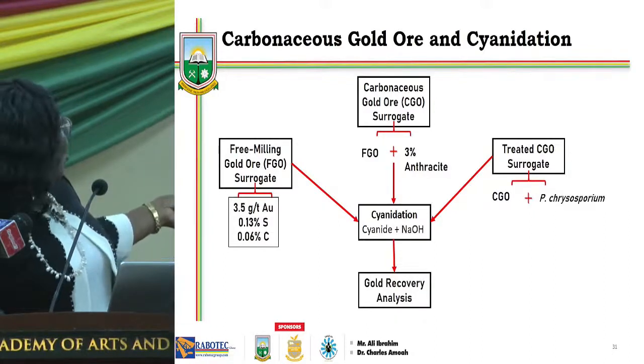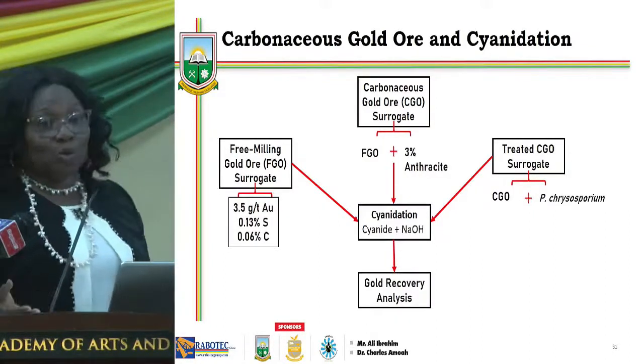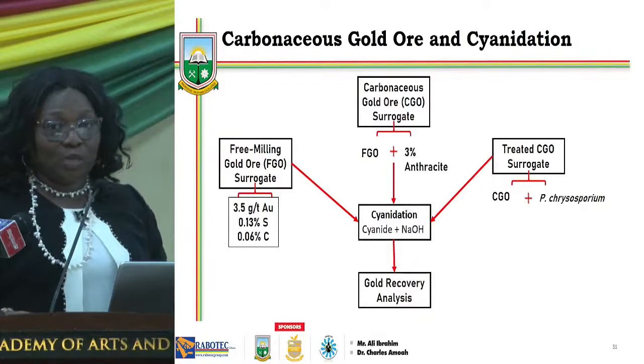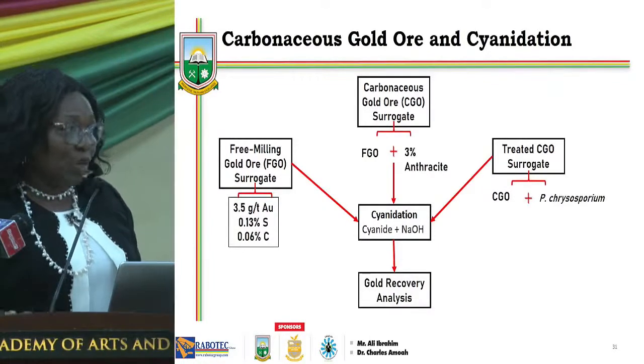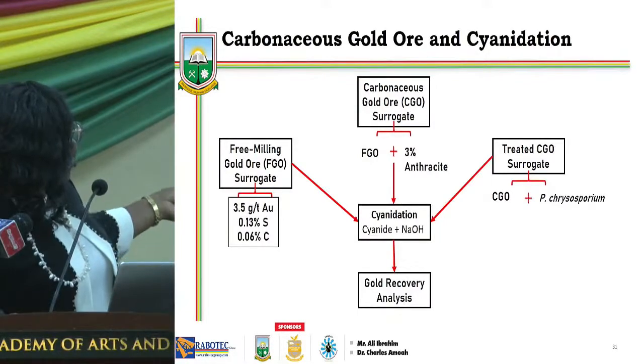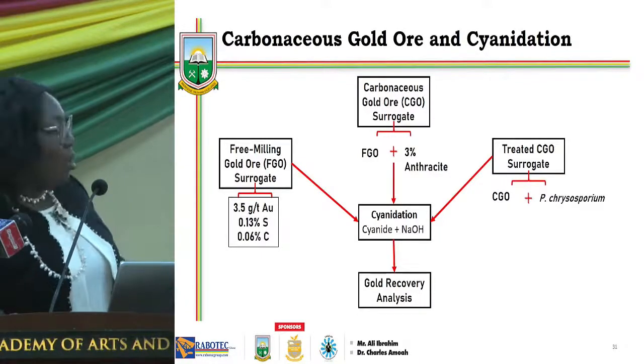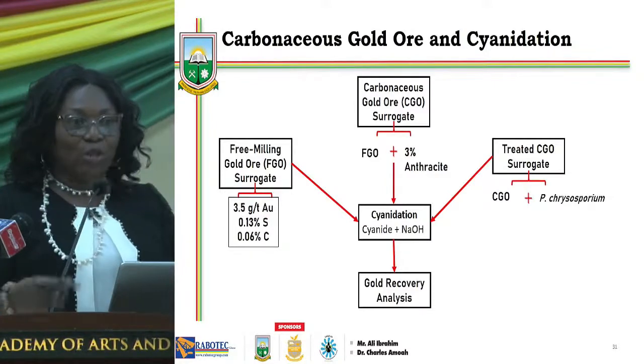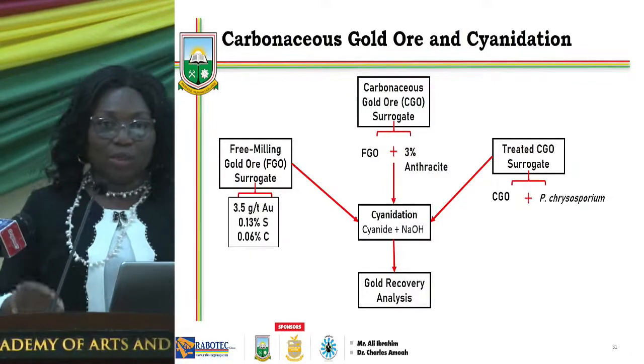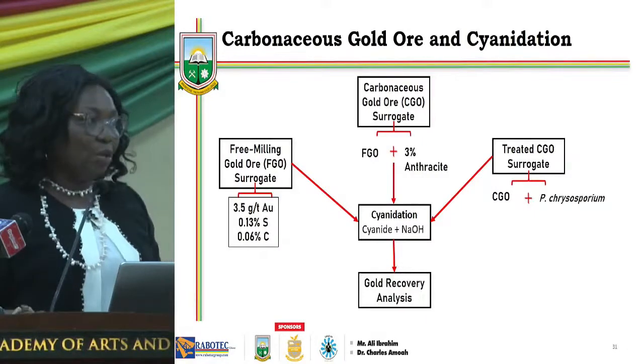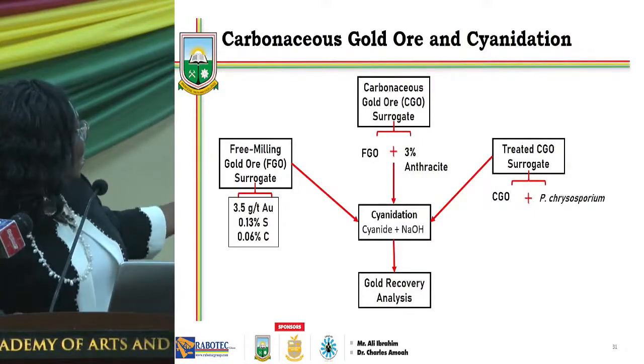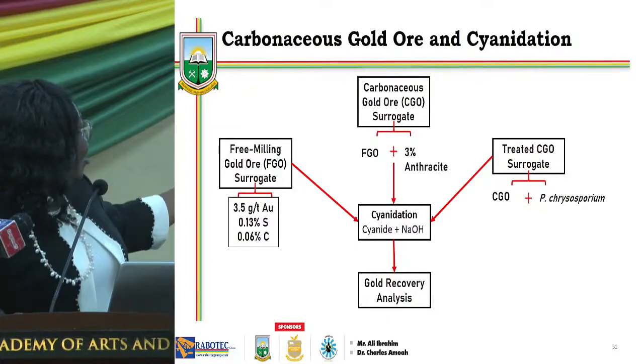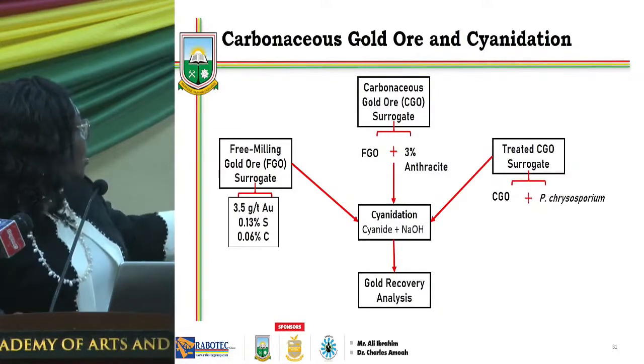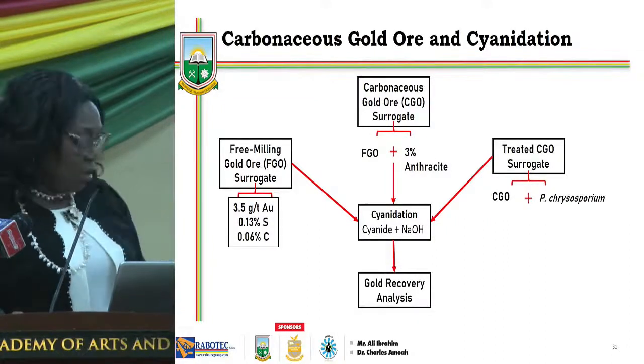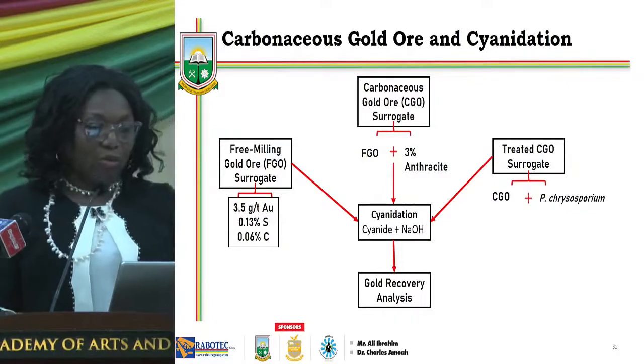So we have free milling gold ore, and that is the easier to treat ore. You put it in cyanide solution, you can recover 95% of the gold. That is a free milling. So we did that, and then we created carbonaceous gold ore by dosing 3% of anthracite into the free milling gold ore. And it also went through cyanidation. Then this carbonaceous gold ore was treated with Phanerochaete chrysosporium, and it also went through gold leaching. So let's see the results.